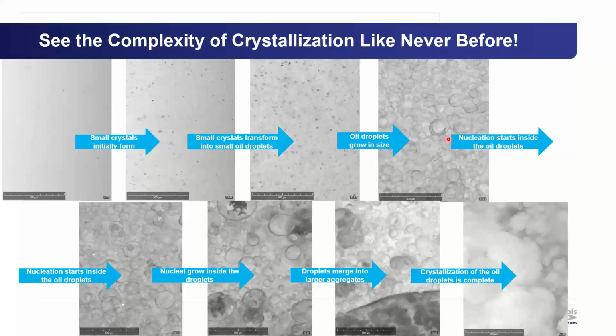And you can see really complex crystallization behavior at this small scale. So this is a case where a molecule was doing a cooling crystallization, initially forming very small crystals, and these crystals over time started to become droplets. These oil droplets began to coalesce and grow in size, creating very high localized supersaturation, and crystals began to form inside these oil droplets. The crystals began to grow inside these, consuming the oil, and eventually the oil droplets aggregate even further, and we're left with just these giant rocks of aggregated crystals, which are really difficult to handle.